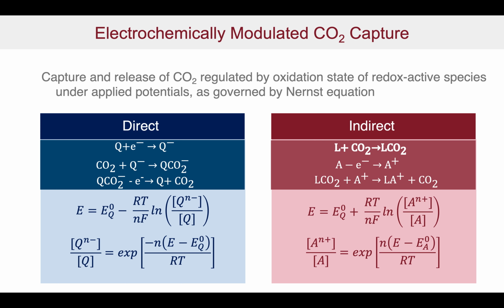Another approach is the indirect approach, in which we would have some component, an amine L, interacting with CO2 to give us a complex, LCO2. That is not electrochemically active at all. But then we have a second species A that can be oxidized to give us an A+, as shown here. When we throw that A+ in with the LCO2, what we find is that there's a strong displacement. The A+ is much more strongly favored by the L than the CO2. So it displaces the CO2 from this complex, and you then get the CO2 coming off as a pure gas again. And then, of course, the A+ can be reduced to regenerate the L. That'll go back to give us other options for CO2 capture. Again, this is all governed by the Nernst equation, as shown here.